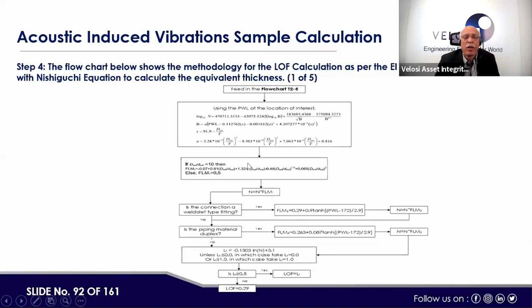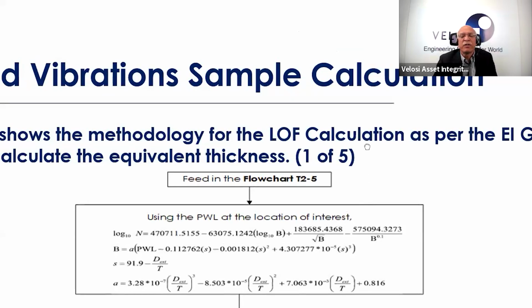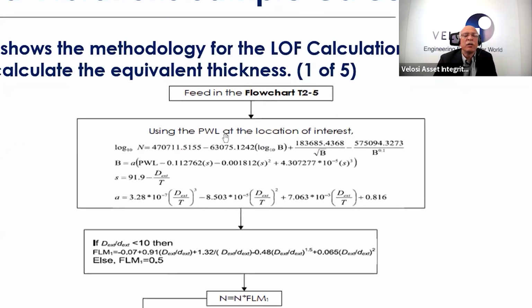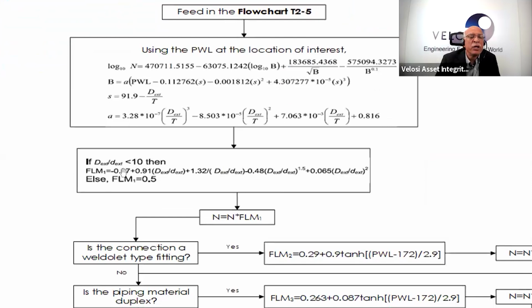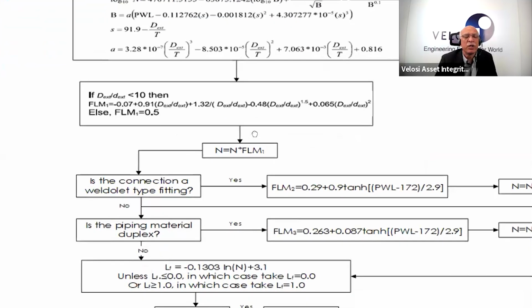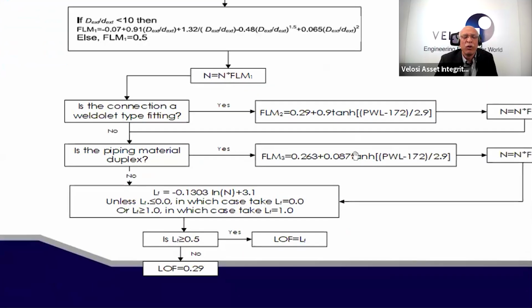So what we are achieving here, for example, from the previous section we came here using PWL at the location of interest, then this is the equation with which the number of cycles is calculated. Then if d over t is less than 10, then this equation, otherwise this equation, and accordingly we will be getting LOF, if it comes less than or equal to 0.5 or 0.29, which is the ideal condition.